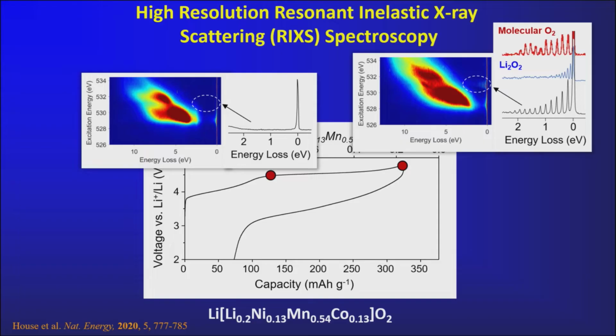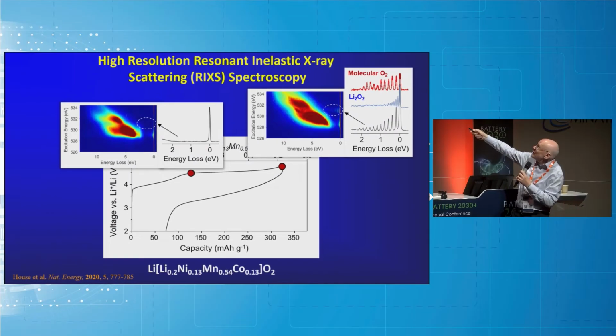Now, this is basically a vibrational spectrum for the oxygen. And if you look at that red spectrum above here, this is the vibration spectrum for molecular O2. That's the vibration spectrum for peroxide, O2 2-. And you will see that the spacings between these peaks, in other words, the vibrational spectrum that we see in this solid material after charging, is the same as that for molecular oxygen. Not for the other species, but for molecular oxygen.